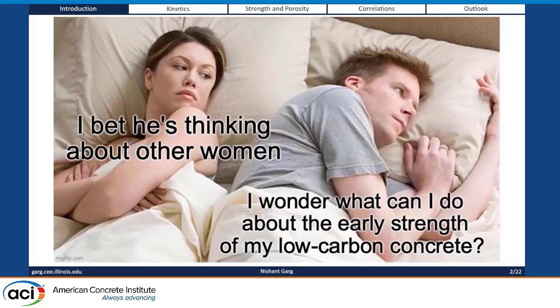When you dilute the clinker to 40, 50% or more, your early strength starts to suffer, and you have to find solutions for that. One of the obvious solutions is, well, you add accelerators or strength-enhancing admixtures, and within that category, there's a newer sort of animal, which is nucleation seeding, and one of them is CSH seeds, and that's what we're going to talk about here.